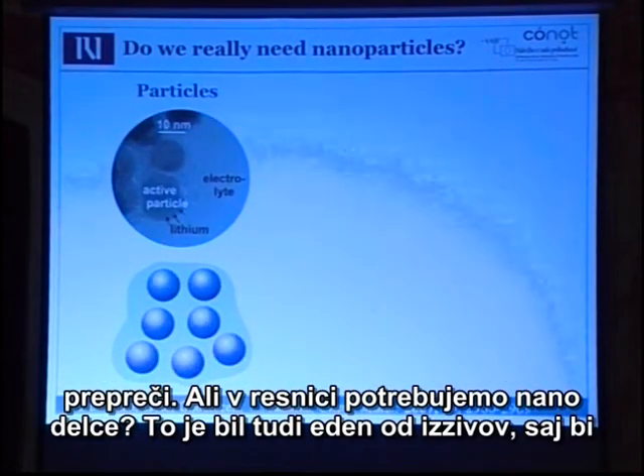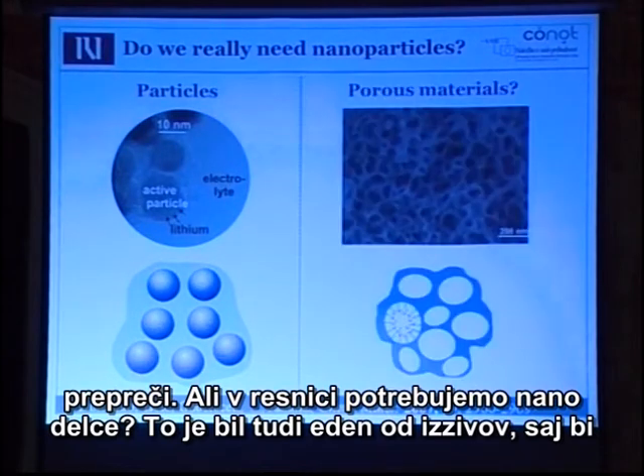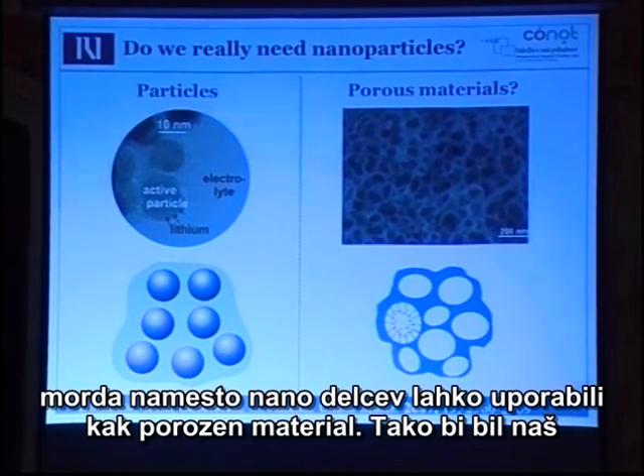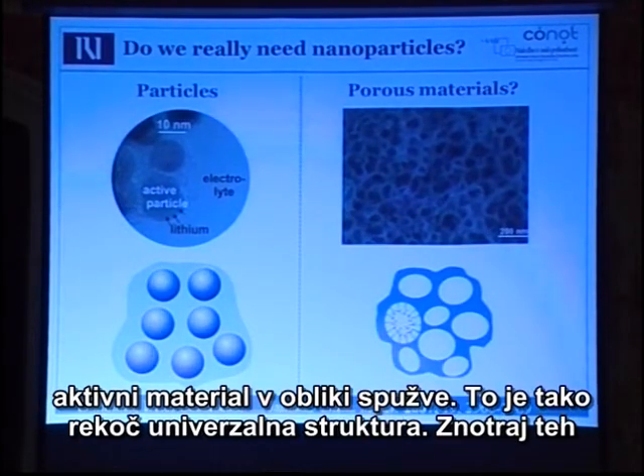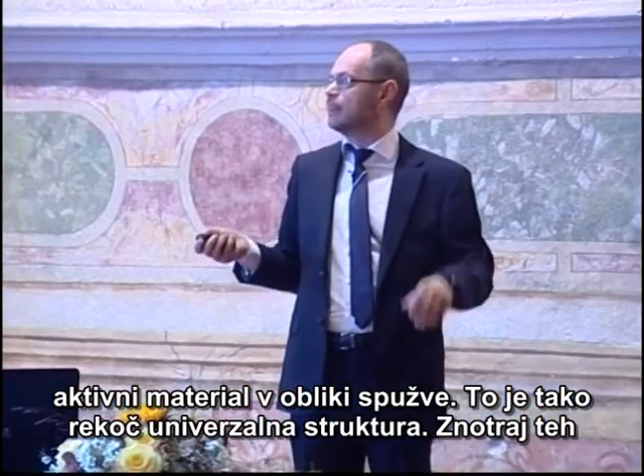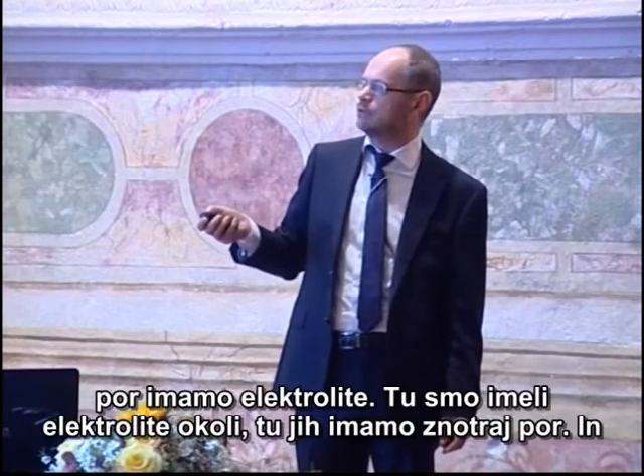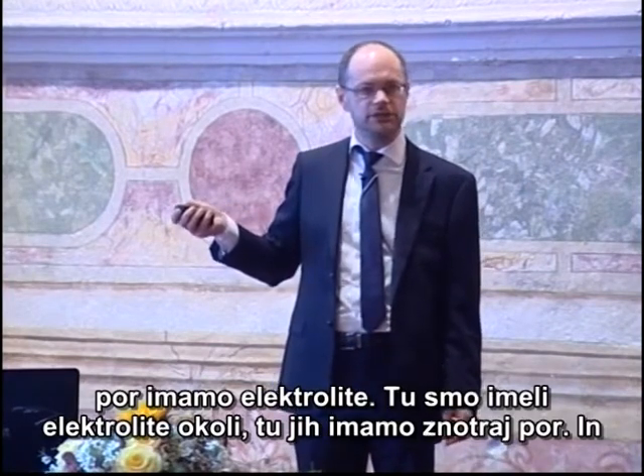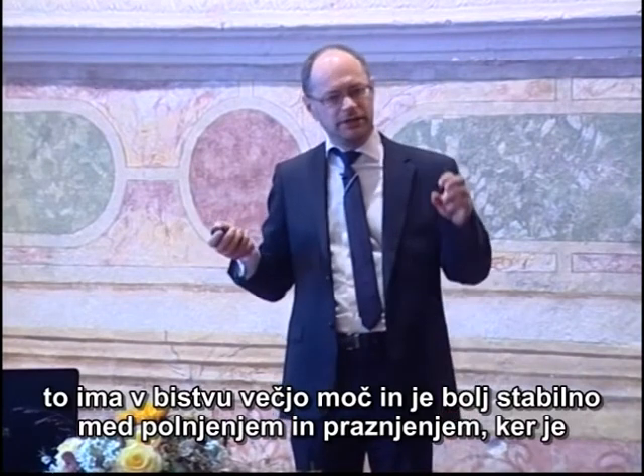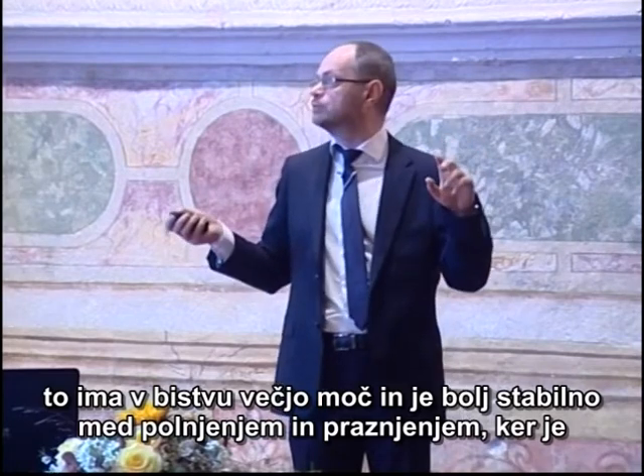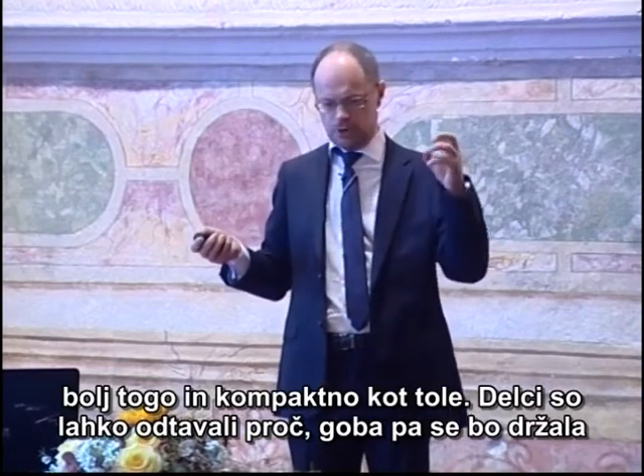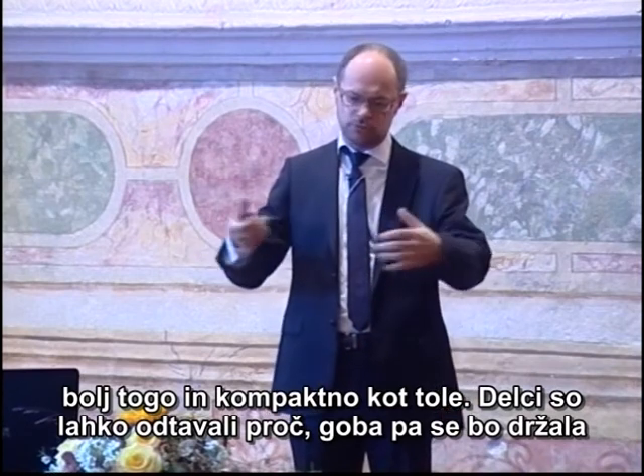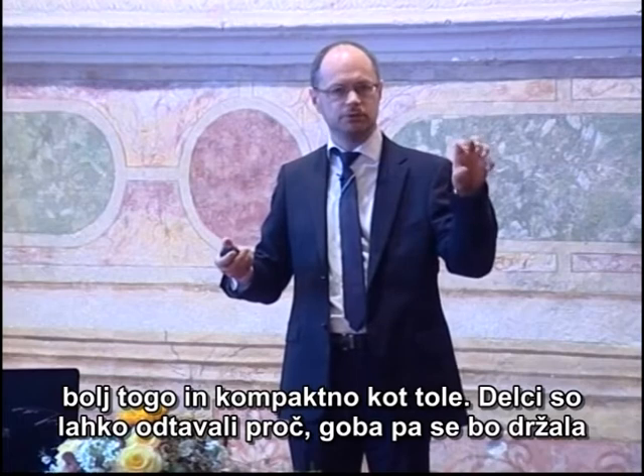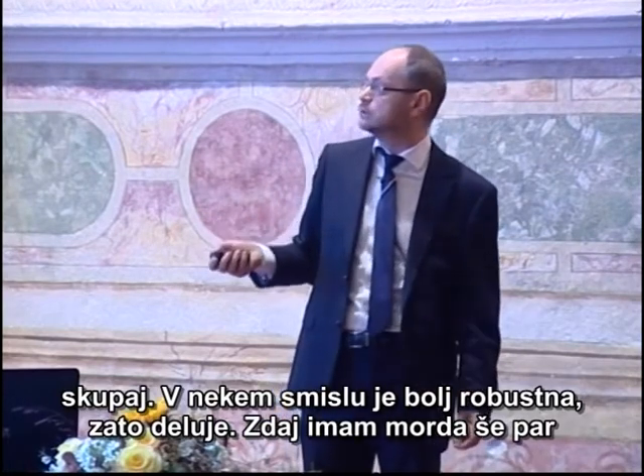Do we really need nanoparticles? This was also one of the challenges, because what you can make is also a porous material. For example, you can prepare, instead of using particles, your active material in a form of sponge. So it's a sort of inverse structure, so to say. And inside these pores, you have electrolyte. Here you have electrolyte around. Here you have inside the pores. And this has actually bigger power, or it is more stable during charge-discharge because this structure is more rigid, more compact than this one. Particles will just float away, but sponge will keep together. So it's more robust in a sense.